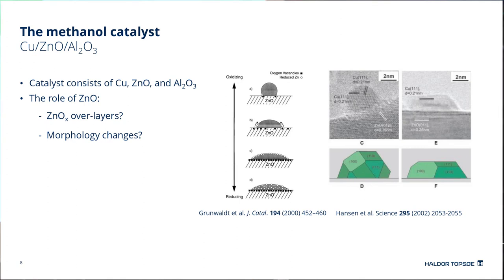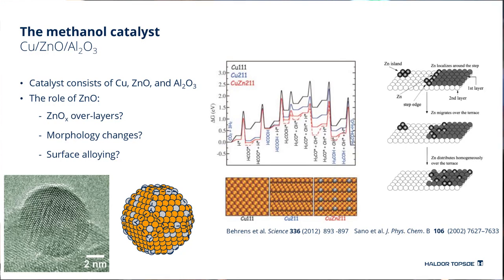We have seen that if you put copper on a zinc oxide particle and you expose it to different reducing and oxidizing conditions, the particles can change shape. So you also have some morphology going on here. So is this really what is going on? Or last, but definitely not least, it has been proposed that zinc and copper can surface alloy.